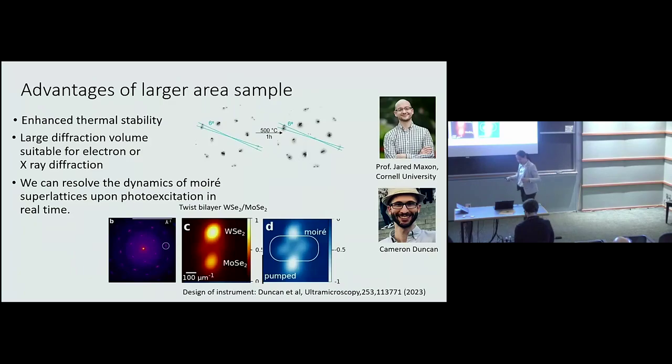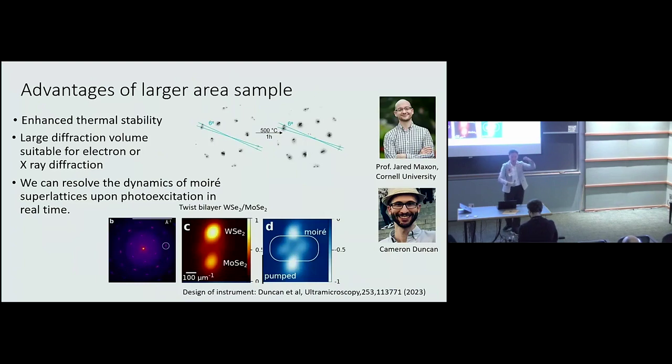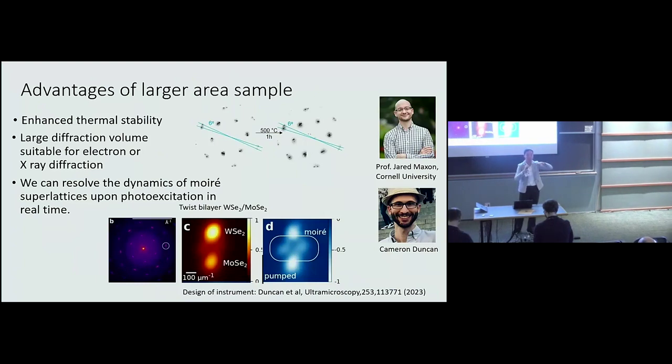Many of you have mentioned the stabilities, and that is indeed one of the major problems in the field of twistronics. Small angle twist bilayers, in particular with a twist of less than 10 degrees, are not the most chemically stable format. The most chemically stable format is when they are twisted back, locked to 0 degrees or 60 degrees, when you have the atoms right on top of each other or perfectly avoiding each other.